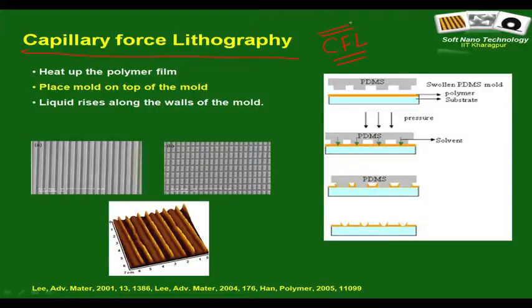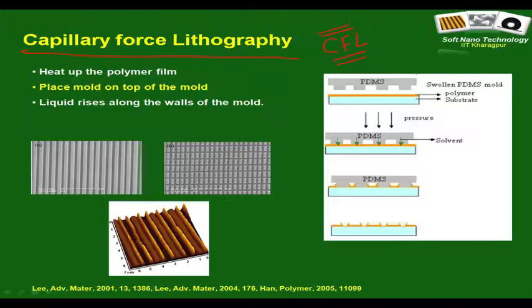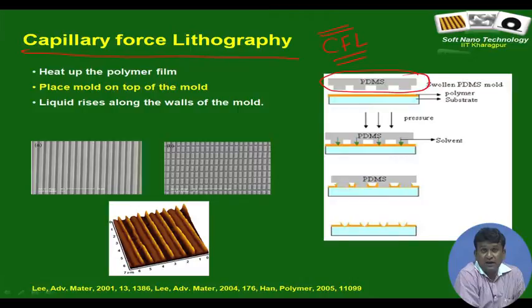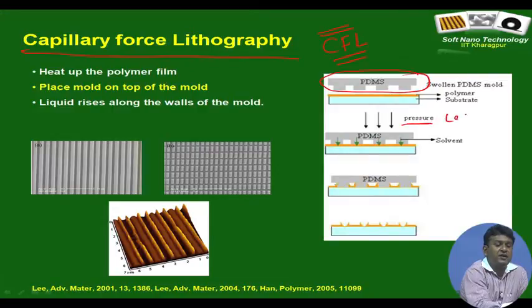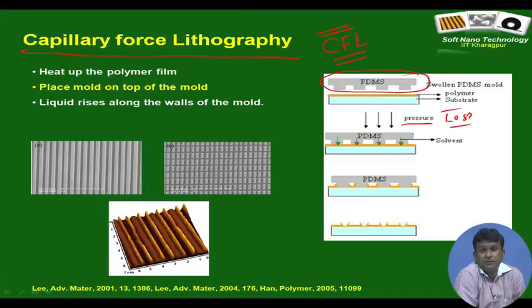So, what it does is take the best practices across the different techniques. It does the thermal cycling or the solvent vapor exposure like nano imprint lithography, but it does not take a rigid stamp, it takes a soft stamp, so that you can peel it off. The problem associated with mold removal as observed in NIL is not dominant. You simply bring a stamp and leave it in contact, with very low pressure, even pressing with your thumb might work. You bring the stamp in contact with the film, which is either heated or exposed to its solvent vapor. Both have their problem of mismatch in coefficient of thermal expansion or swelling, because if you expose to solvent vapor, the film swells as well as the stamp swells, because it is a Sylgard stamp, right, and then you do nothing.